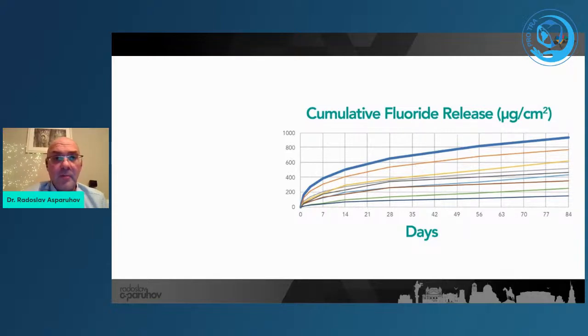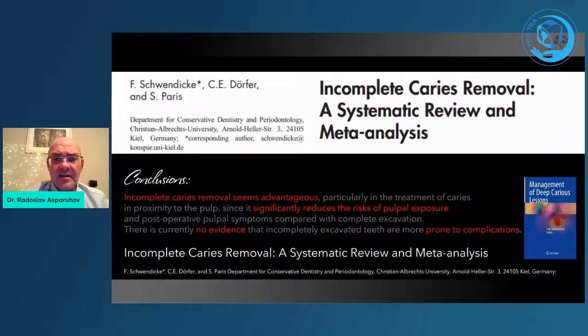So what happens when we have an incomplete caries removal? When we are close to the pulp and we do not want to risk pulp exposure. I am very happy to share the result of a systematic review done by Falk Schwendicke, and one of the conclusions in his study and this review is that incomplete caries removal is giving very many advantages. One of them is significantly reduced risk of pulpal exposure, and postoperative symptoms are much less compared to complete excavation. There is no evidence that incompletely excavated teeth are more prone to complications nowadays.